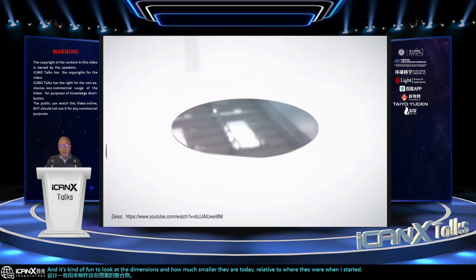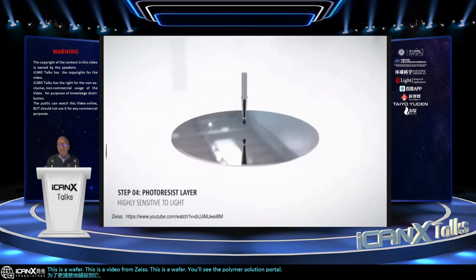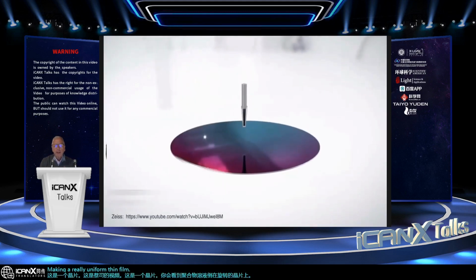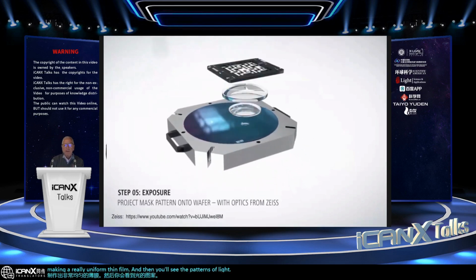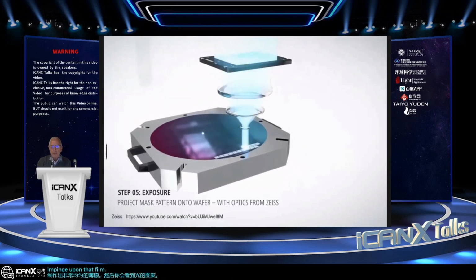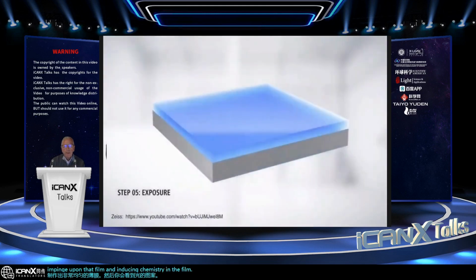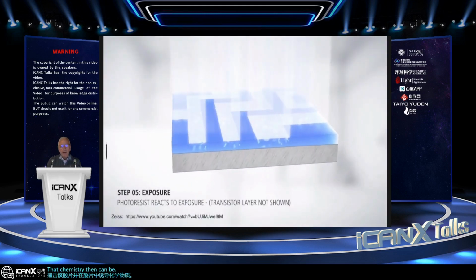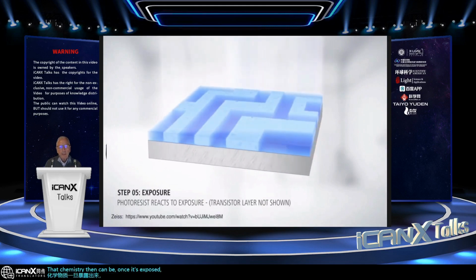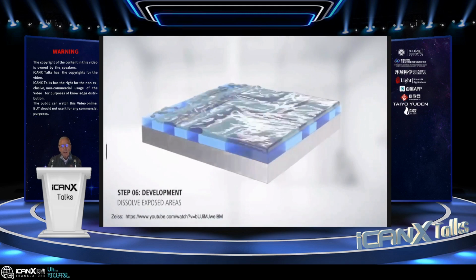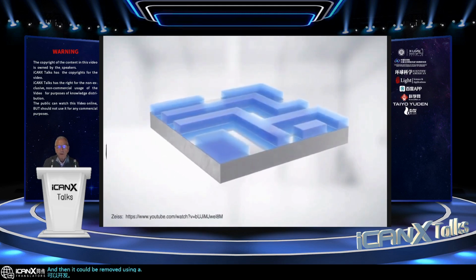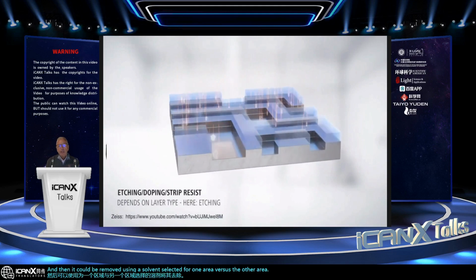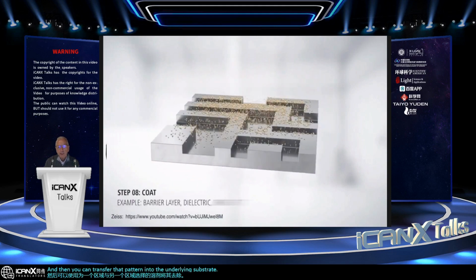And just to capture it a little bit more clearly, this is a wafer. This is a video from Zeiss. This is a wafer. You'll see the polymer solution poured onto a wafer that's spinning, making a really uniform thin film. And then you'll see the patterns of light impinge upon that film and inducing chemistry in the film. That chemistry then, once it's exposed, can be developed, and then it could be removed using a solvent selected for one area versus the other area. And then you can transfer that pattern into the underlying substrate using etching technologies.